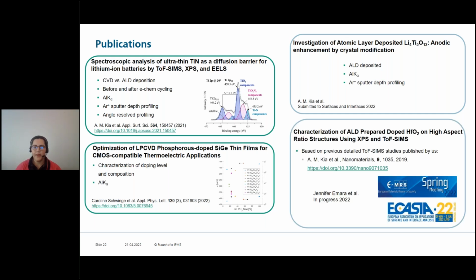There is also a publication that is in the pipeline right now, where we prepared doped hafnium oxide using ALD on high aspect ratio structures using XPS and TOF SIMS. So we characterize them using these two techniques and we are comparing them. And this paper is based on a previous detailed TOF SIMS study that was published by us about 2 years ago.